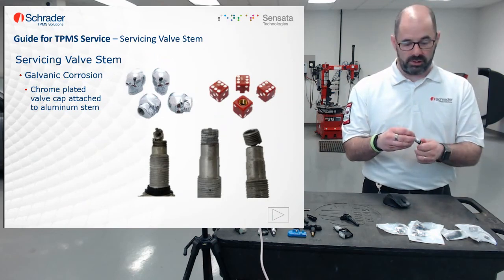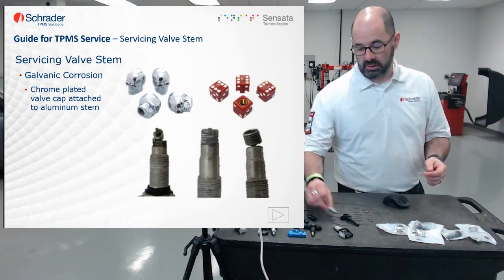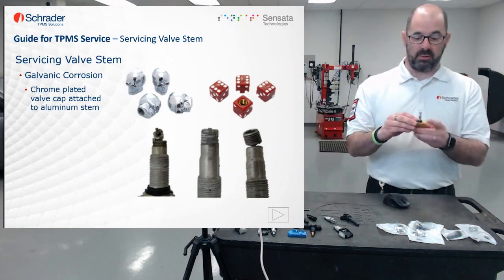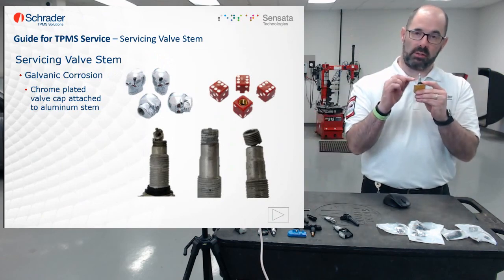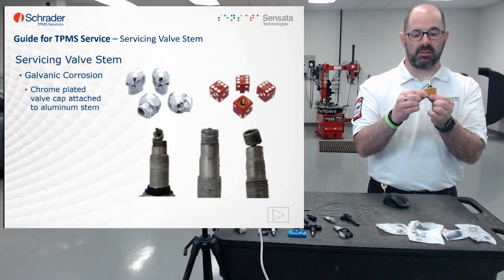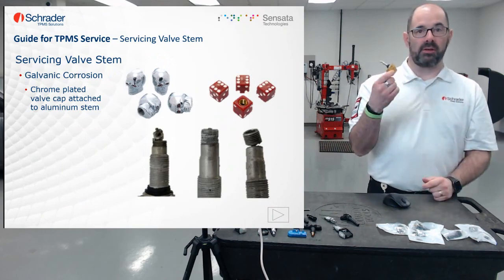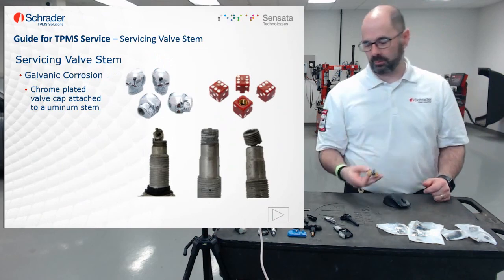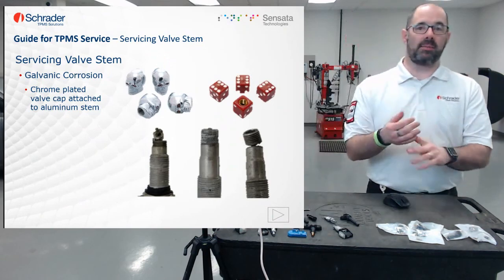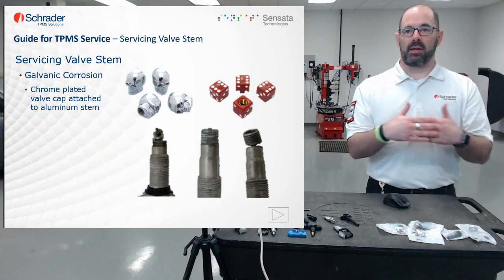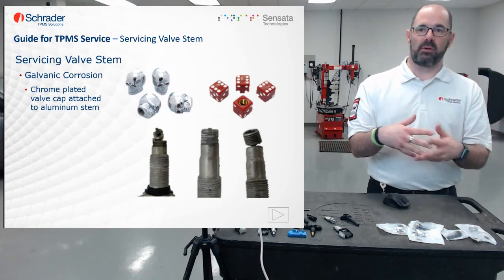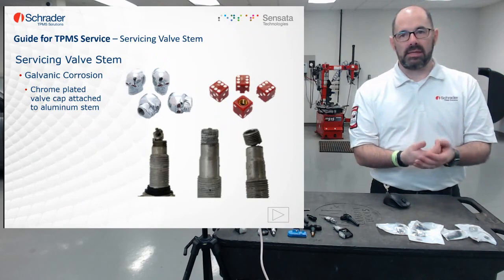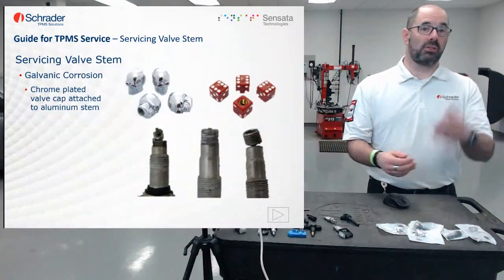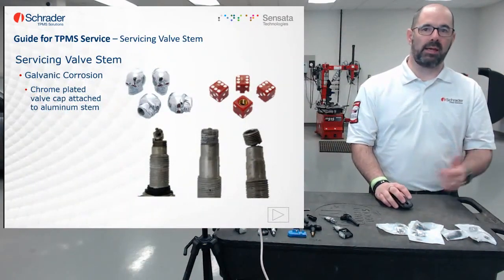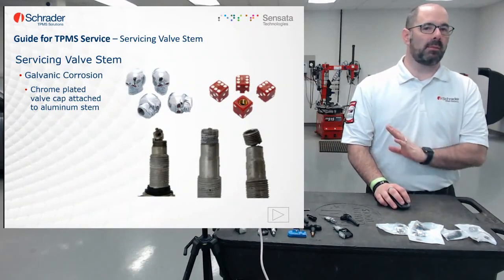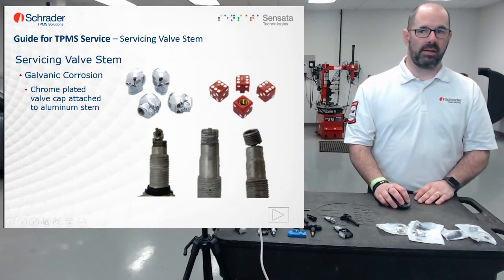You'll try to remove it, but he needs to know that if you're ever dealing with a one-piece module where the stem is permanently attached to the sensor and you break the stem, you're going to need to replace the whole sensor unit. Galvanic corrosion is something you get when you have 2 dissimilar metals. When you mix 2 dissimilar metals and you add a little bit of heat, a little bit of moisture, just like the example we have here, a chrome-plated cap on an aluminum stem is a perfect scenario for galvanic corrosion.